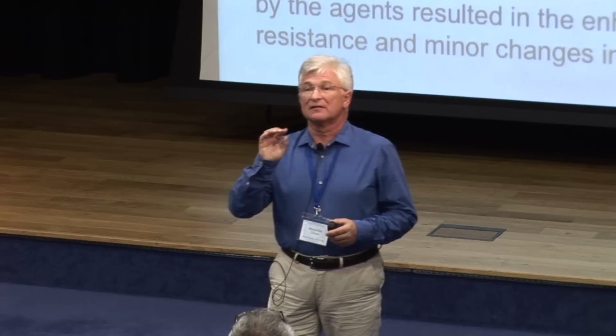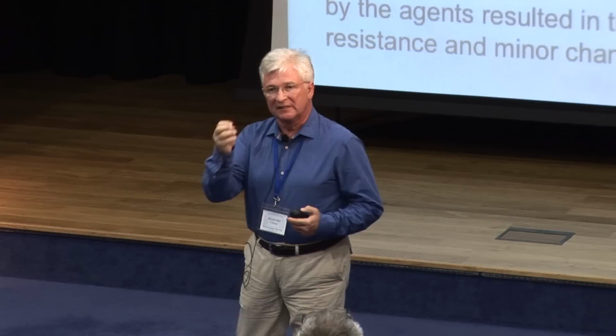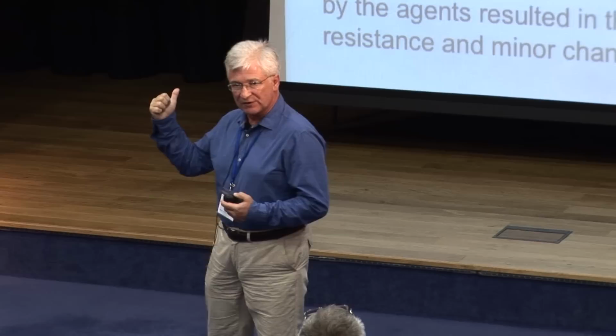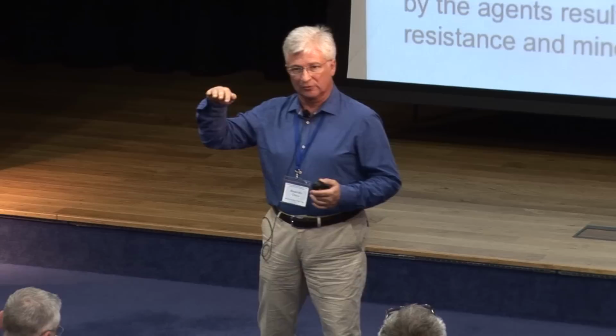But it's necessary to stress that it's impossible to use cast metal as a universal metal. It's necessary to search for special conditions for this tool. For example, the geometry of the tool is very important, and cutting conditions are very important. It's necessary to use this cast metal only in conditions where, for example, strong abrasion wear dominates and the level of dynamic loads is very low. Then such a tool is very good for improving durability in general.